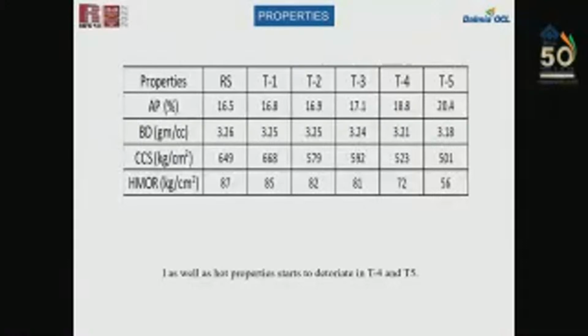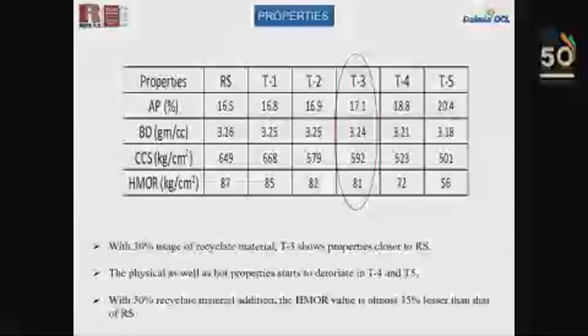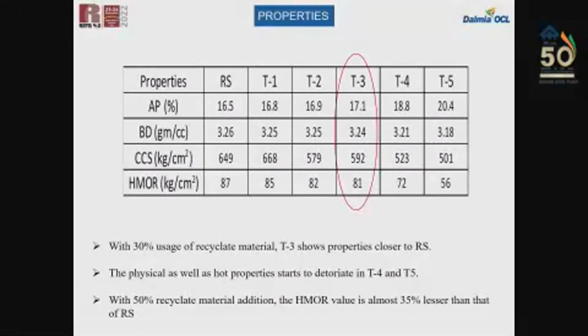So here are the physical properties which we are seeing. The thing is that T3 is giving properties which are almost nearer to the RS. RS is the standard one, which is after 30% use of the recycled material. When we go to 40%, there is a very high increase in the apparent porosity and decrease in the HMOR. These are the two main properties which are required in the RH degasser for better performance.